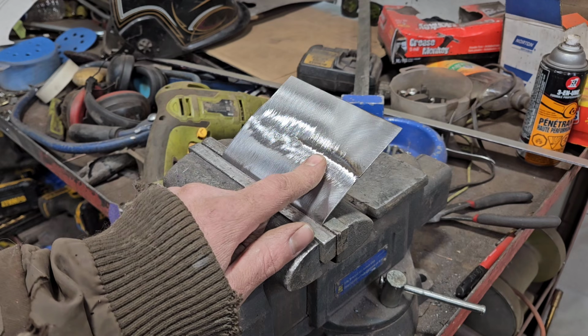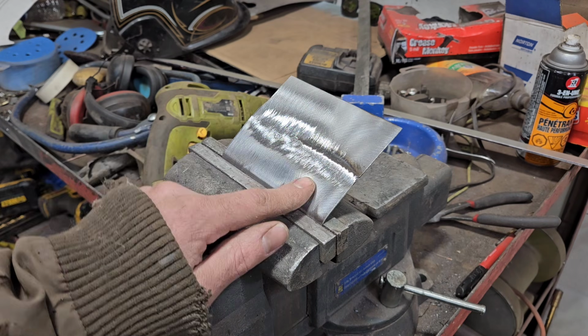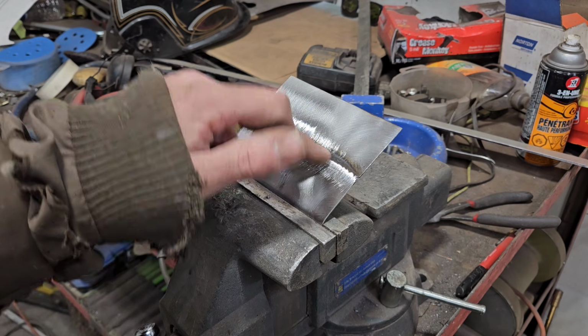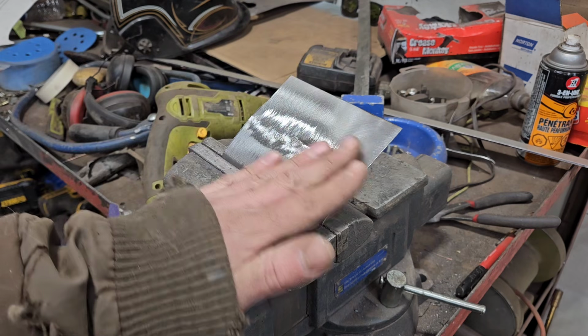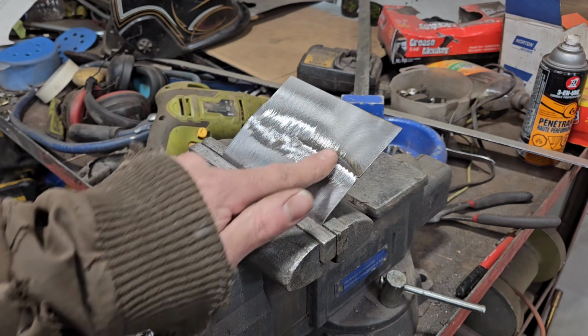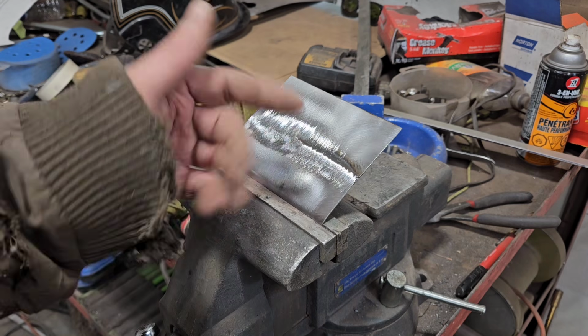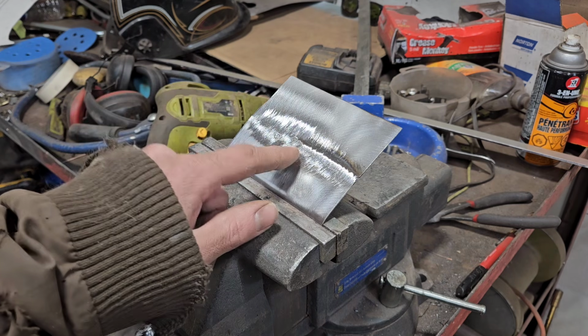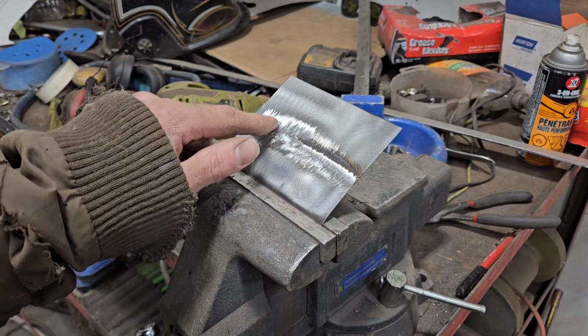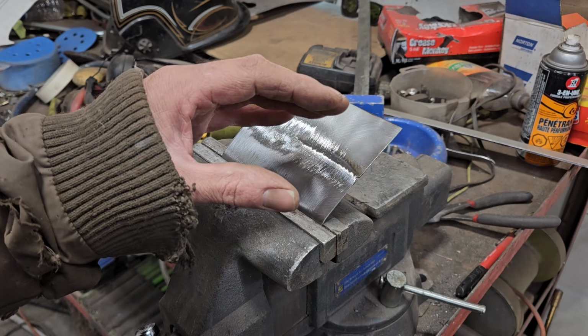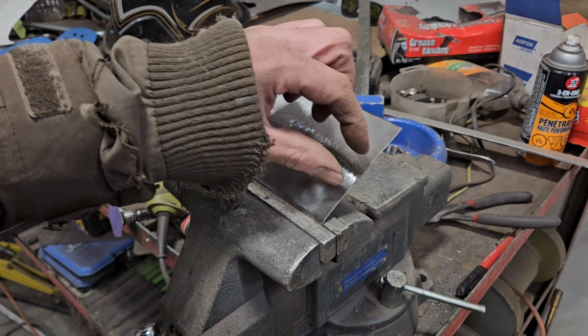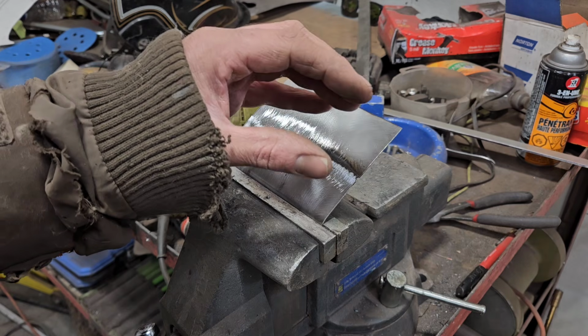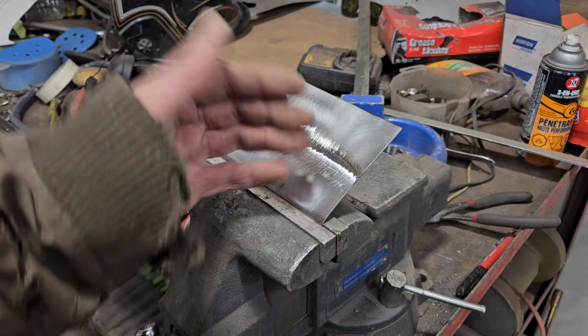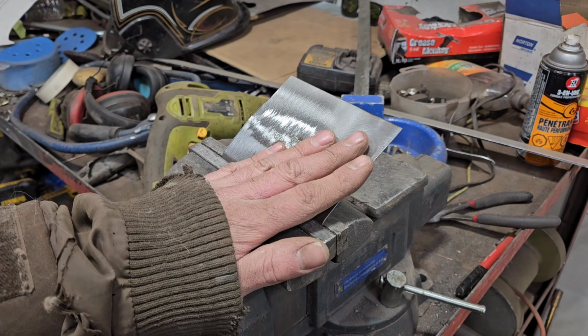Just about all the way through. So that's not good. The other thing I've seen folks do when they have this type of situation is they'll go back in and add more weld on this side and then grind it, add more weld and grind it until this disappears. Well, there is a bit of a problem with that, and the problem is that every time we weld something, the heat from that welding is going to cause the metal in this area around the weld, and the weld itself, to shrink, which is causing damage to the panel.